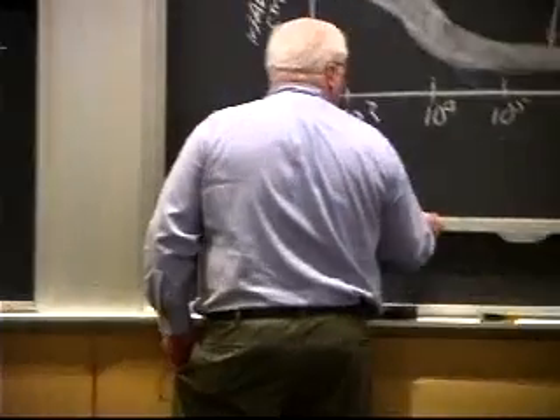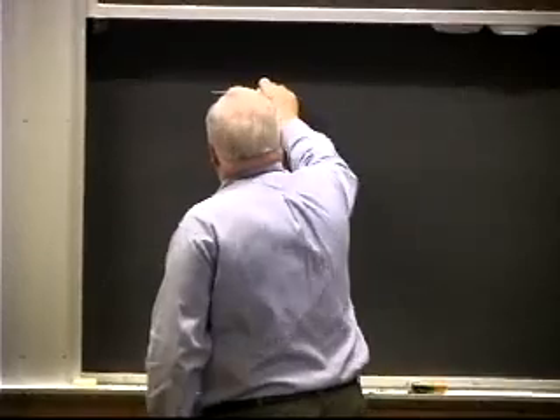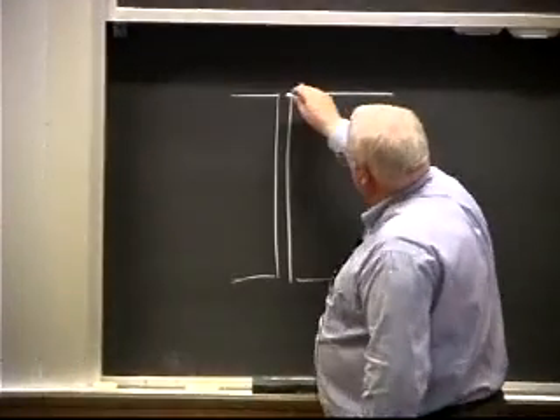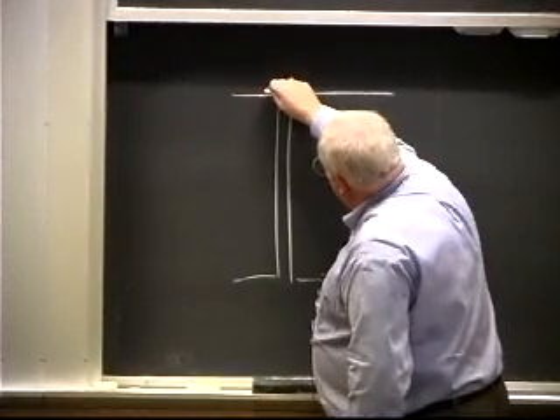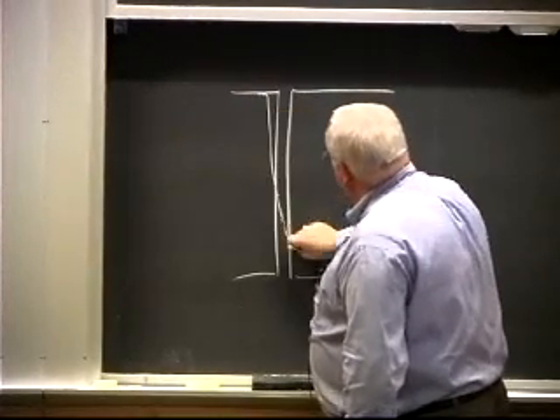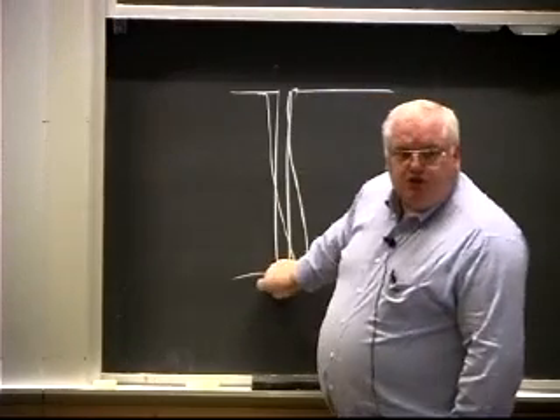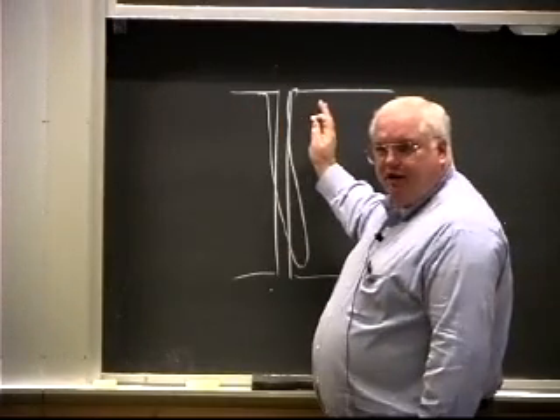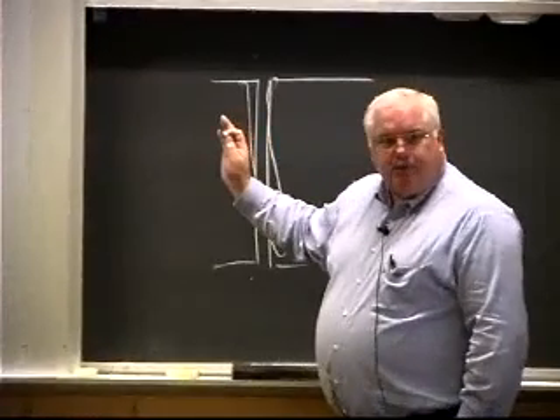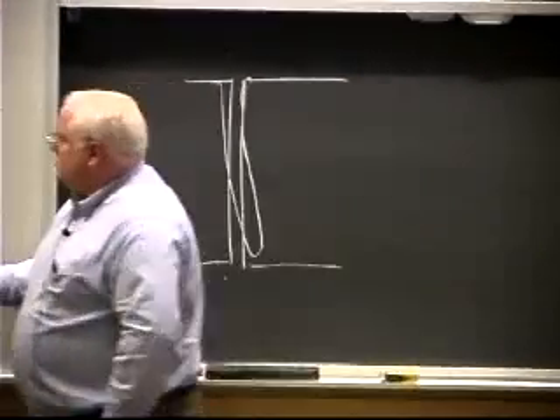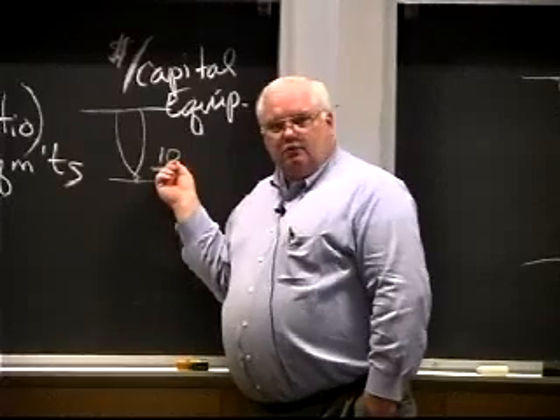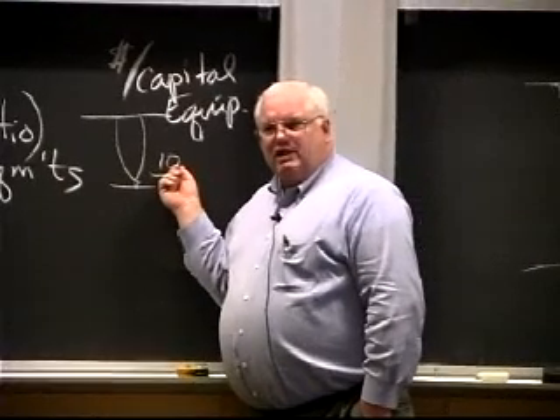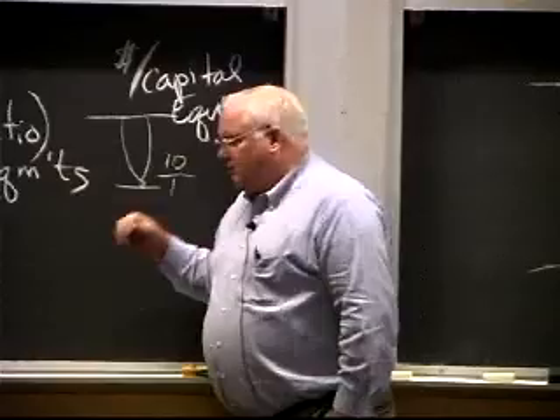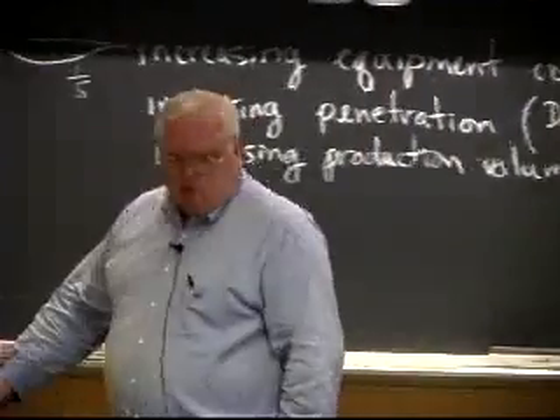The problem with doing something like that is if I actually wanted to make a real part, and I had something that was this thick, and this is not 200 to 1, in fact this is probably only 20 to 1 or something, and I put a weld in there that looks like this, if I'm off by just a little bit, I'm going to miss the joint. I can miss it angularly, I can miss it this way. There's no flexibility in the fit up when I go to a super aspect ratio. So even though I can get 50 to 1 without much difficulty in electron beam, I can't use it in a practical sense. So 10 to 1, maybe 15 to 1 is about the highest you'll ever see people go.